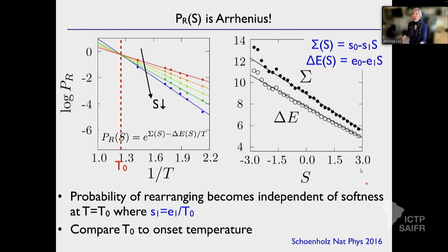Yeah, so the properties are very dependent on that. For example, if you take this system and you quench it very rapidly, then the average softness is quite high. But if you quench it very, very slowly, equilibrating extremely well down to a very low temperature, then the average softness is very different, much lower. So depending on how you prepare your system, you can prepare it with more or fewer defects. And that makes a huge difference to behavior.